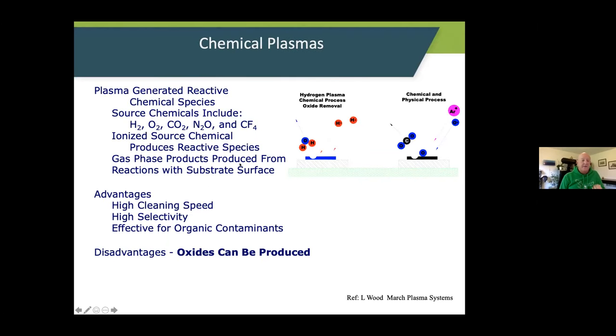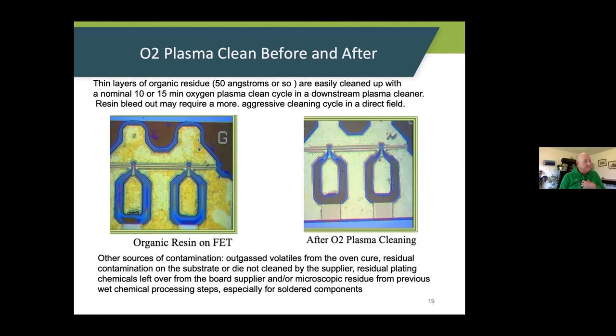Oxygen, on the other hand, chemically combines with the organic contaminant. So if it's resin that you can't see, or it's something that's outgassed, or wherever it comes from, with oxygen, you're going to combine with it and then suck it out in the plasma cleaner. And my experience has been it's a far more effective way of plasma cleaning.